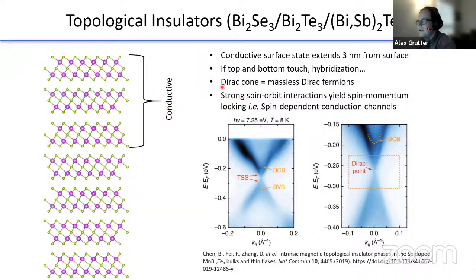But assuming your topological insulator is thick enough, what you should see is that in between your bulk valence and bulk conduction bands, and this has been seen many, many times in ARPES for a variety of different systems, you should have a Dirac cone with a linear dispersion relation connecting effectively the bulk valence and conduction bands. And in this state, you have all kinds of really interesting properties and interactions. And this is characterized by very strong spin orbit interactions, which gives you spin momentum locking, so that your conduction channels are in fact spin dependent.